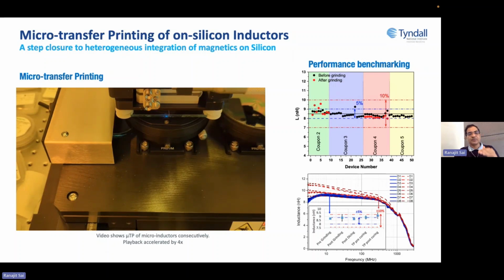Now, we knew that we have a magnetic material which is very delicate to different processes and so on. Its magnetic property gets upset, and if the magnetic property is not held, then your inductor property will not be intact. We have done a thorough statistical analysis at different stages, and I have seen that most of our variation is within some 5% or so, whereas if you go to any data set, you will see inductor specification which is altering around plus minus 10%. So we are much better than off the shelf inductors in that sense.